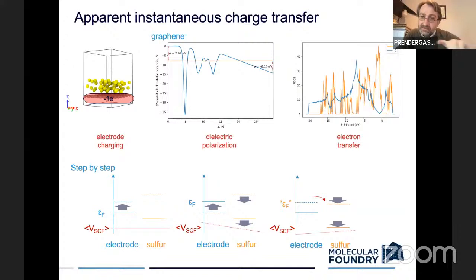and there is this kind of dielectric or region of insulation between an electrode and the system that you care about in the electrolyte, constant potential may also enhance this problem. And so it's not that constant potential is wrong, there's nothing wrong with it, but it's the assumption that you have a shared and common Fermi level across the entire system, that your electrons are at equilibrium. That's the issue. And there would be a long time that it would take for electrons to actually reach that outer surface. So we need to take that into account when we design these simulations.